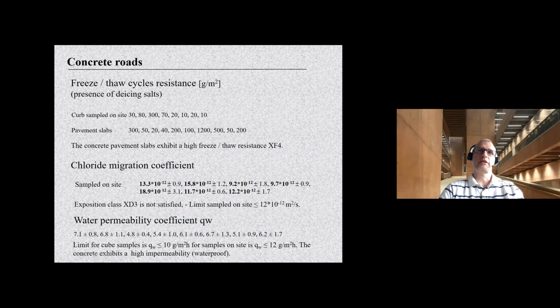Concerning the chloride migration coefficient, some of the values were above 12 times 10 to the minus 12 square meters per second. We can see some values that range between 13 and 15, and some of them reach 18. And the exposition class XD3, which is the maximum exposition class for cementitious material resisting the penetration of chloride, is not always respected.